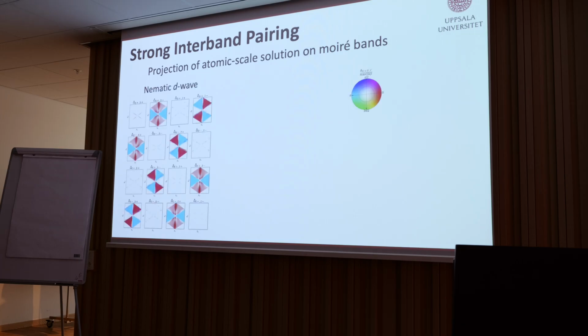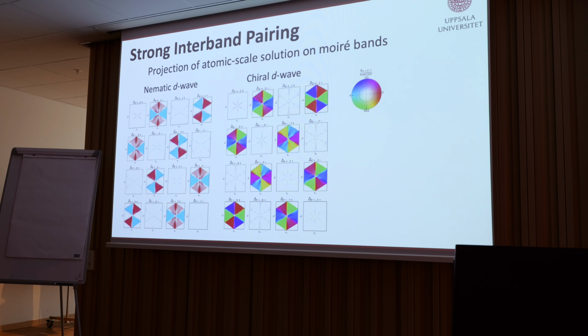So here is a nematic d-wave projected on the moiré bands. We have four bands, and I have labeled them B plus, B minus, T plus, and T minus, where B and T are bottom and top, and plus and minus are the valley index. The chiral state is here, and I try to use a color scale. You see these ones are all real valued, and these ones are complex, they wind around. So you see the chiral keeps the six-fold symmetry. The nematic has either, let's see, this is d x squared minus y squared, and this is d xy.